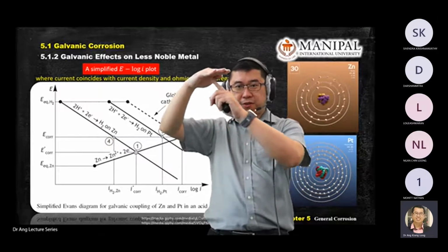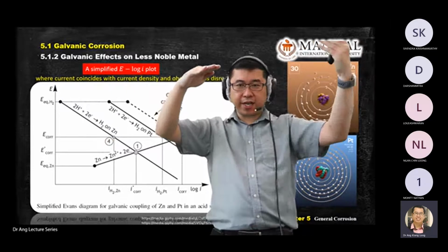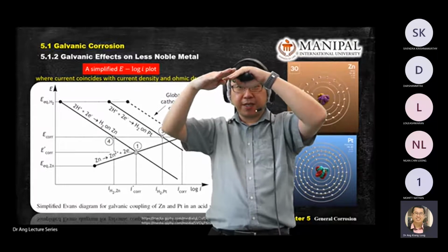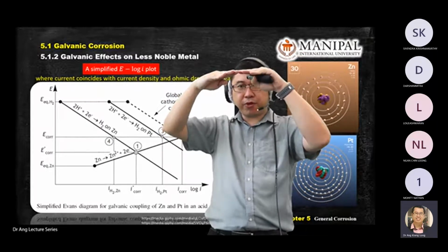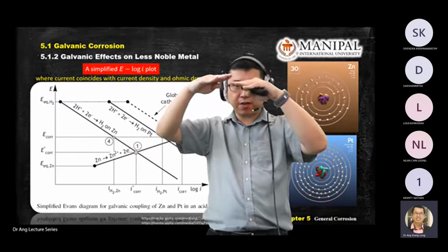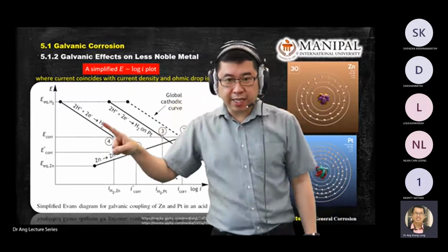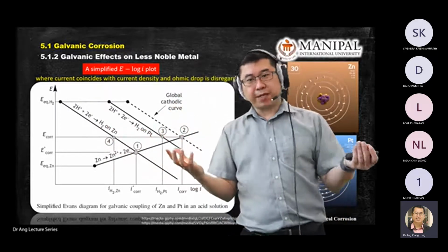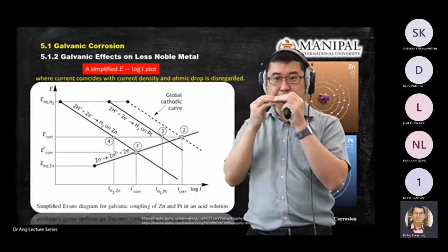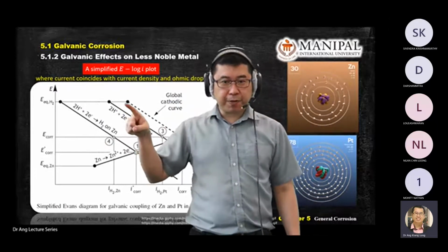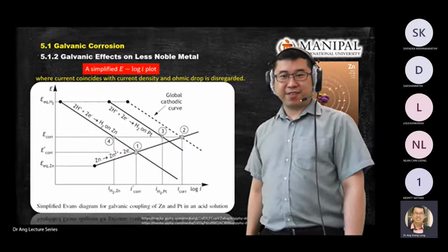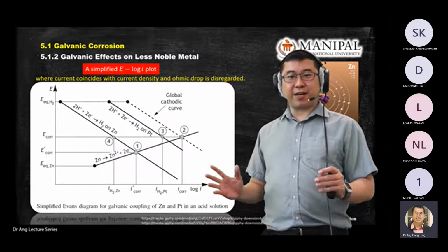Electron goes up, transfers, but the cathode does not do anything. It just, okay, come receive. But the electron cannot jump over into the solution. It can only go to the surface of the platinum and meet up with its friend, positive friend, which in this case, in the acidic solution, is the H positive. So that's why in this line you see nothing happened to platinum, but something happened at the surface of platinum, where the electron meets up with its good friend, positive friend. H positive plus electron, you get hydrogen.